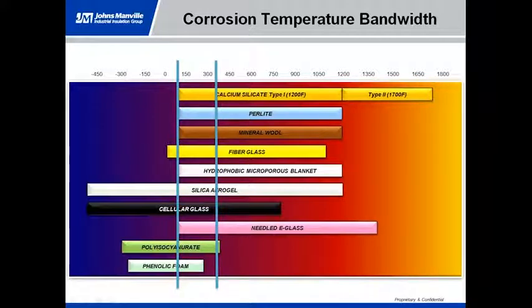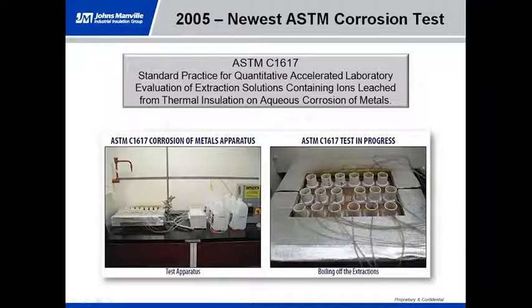And again, every insulation type in just about that temperature range is going to fall in that, whether it's a polyiso foam or a calcium silicate pipe insulation. Now, there's a new method that was developed by many manufacturers, and corrosion testing is always a problem because you always want something that's quick enough to be able to model real life, but also has to be realistic and applicable. In this case, this test method is applicable to carbon steel. The advantage that it has is it's more quantitative than qualitative, as you have with some of the other methods. And it's developed mostly for carbon steel, which typically isn't the case. There aren't as many test methods out there for that.